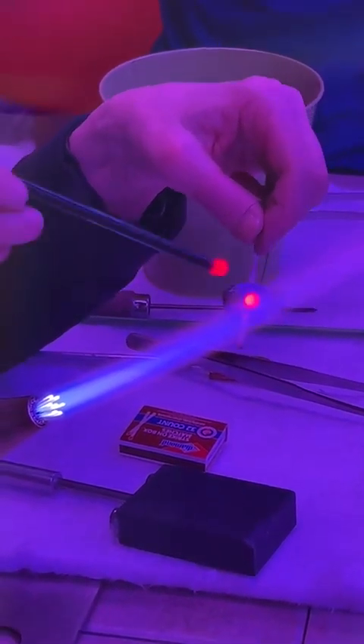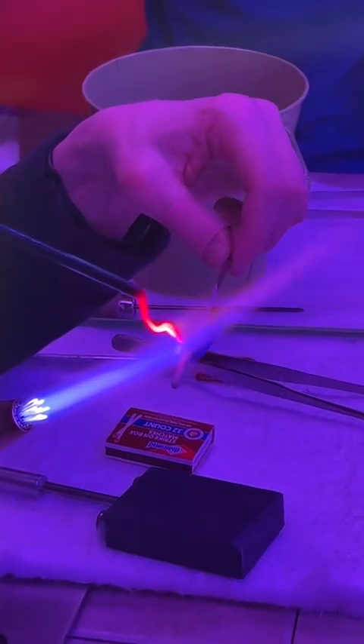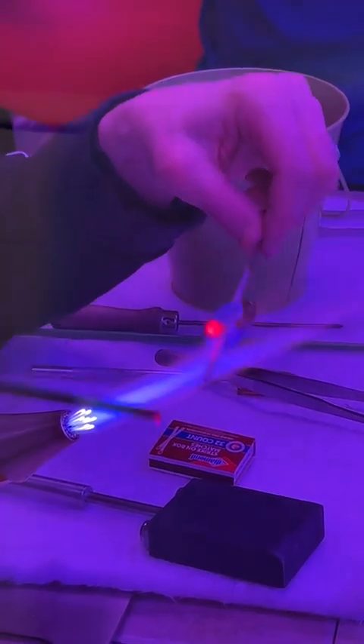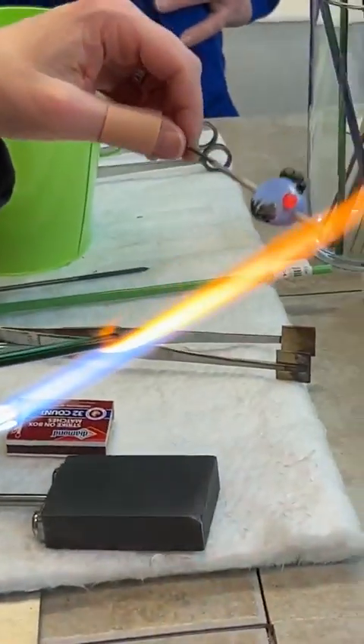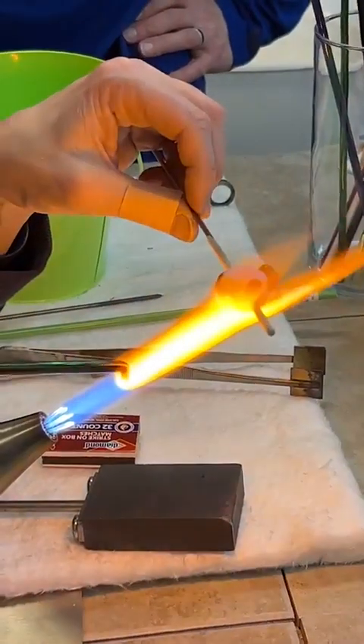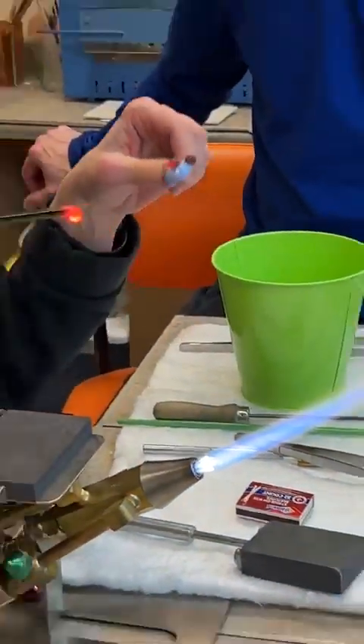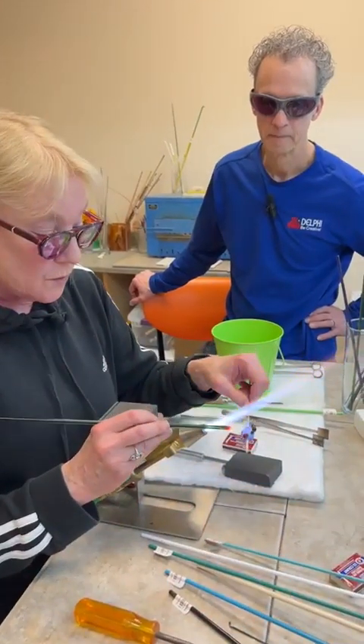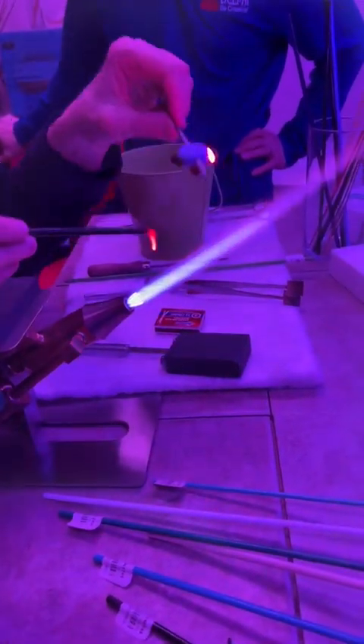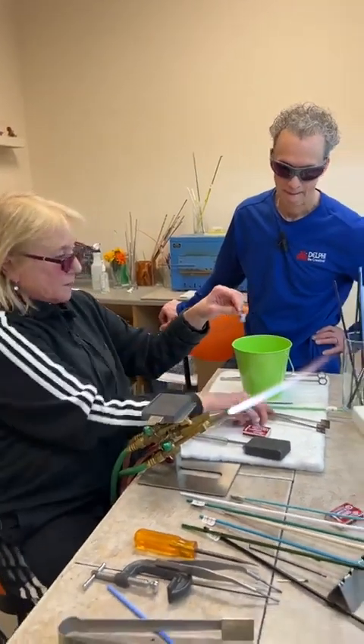I did a dot for the back tail fin. I'm not forgetting about the fins — they're there, but I'm not flattening them yet because once I flatten them they're thin and they lose heat really quickly. I wait until I'm ready to do them all at once. Once I get those flattened, I'm going to have to keep flashing them to maintain heat.